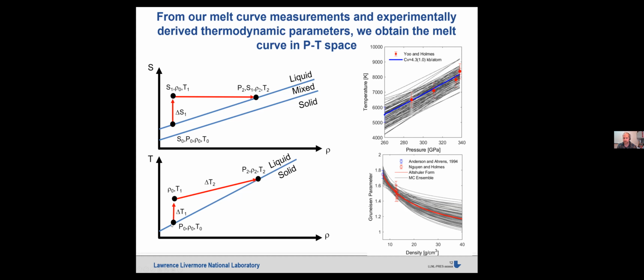Okay, so to get the temperature increase by adding this delta S1 of entropy change, the entropy is just CV over T dT, so it requires the heat capacity. Then the temperature change along an isentrope, you can look at the thermodynamic definition of gamma, which is d log T over d log V. So we know we need the isochoric heat capacity near our reference point, and then we also need the thermodynamic Grüneisen parameter over this range of density space. And we also need, I would say, the temperature reference point on the melt curve.